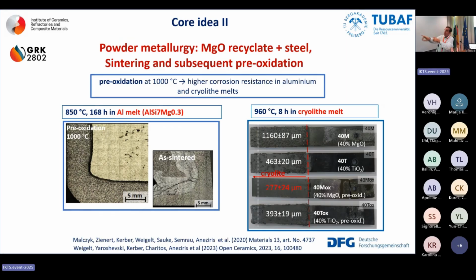Okay, let's go to the marriage with MgO recyclate with steel. You have to sinter it. Somebody would say, which temperature? Not 1600, the steel is away. 1370, 1400 maximum. Where do you sinter it? In argon atmosphere, in a carbon heating element containing furnace.